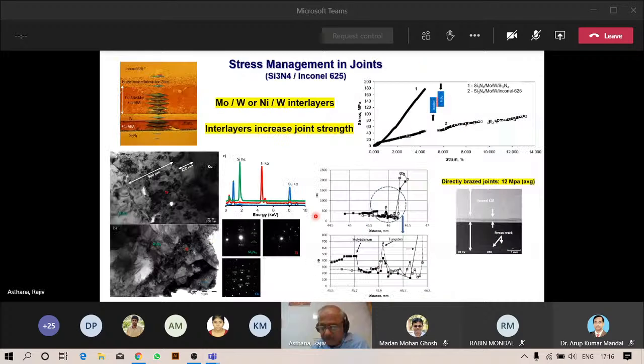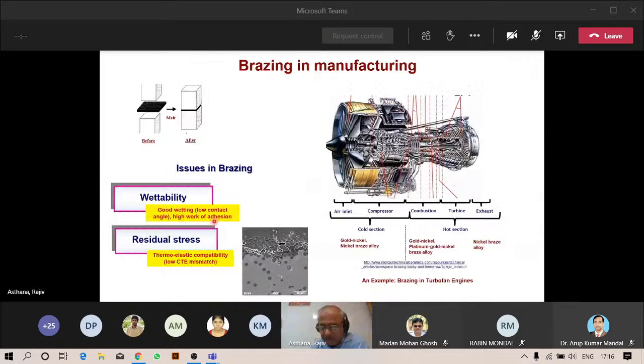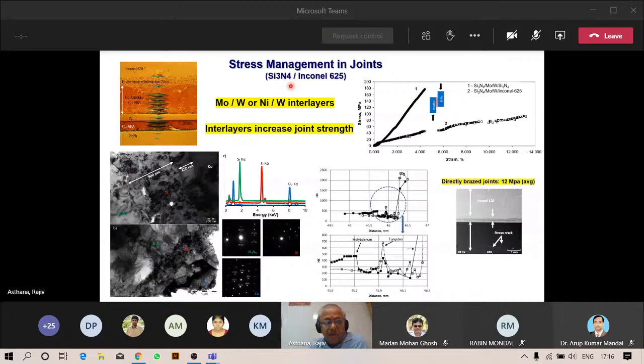There are several different ways that people have been using to minimize or manage residual stresses in joints. So we looked at silicon nitride to Inconel 625 system, a nickel superalloy. And what we found was that if you directly brazed Inconel to silicon nitride, the bonded region looks fine, but the ceramic is fractured because of residual stresses. So stress cannot be accommodated by the thin braze layer, and we end up with a crack. And if you try to test this for bond strength, you end up with very, very low strength in the joint.